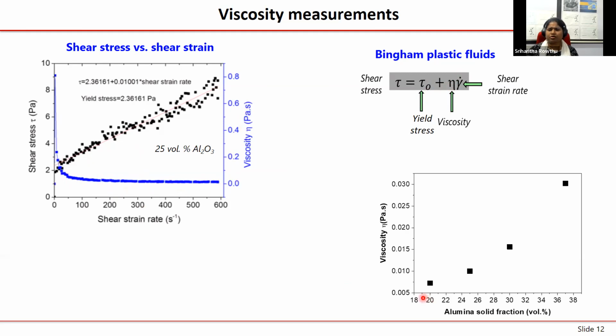Now we can change the alumina solid fraction from a small value up to some 37-40 volume fraction or so, and see that viscosity is consistently increasing as you increase the solid fraction, which is pretty much obvious. Now, this is actually my PhD work, so that's why I'm referring to it as I. What I have done is take samples with different viscosities, cast them into molds, let them dry, also sintered them, and looked at them in SEM.